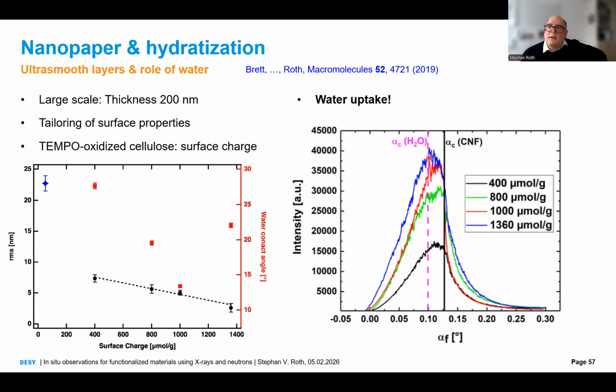This is water. So we can detect water with X-rays. And we could calculate the water content between 4 and 16% in our cellulose nanofibril layer. So this was actually the first time we could detect water. And secondly, we confirm this is measured under dried atmosphere. You can never dry cellulose. There's always water in cellulose.